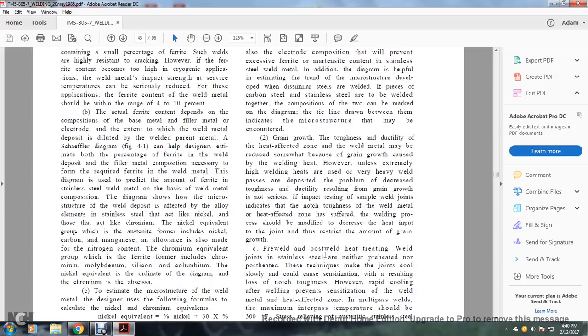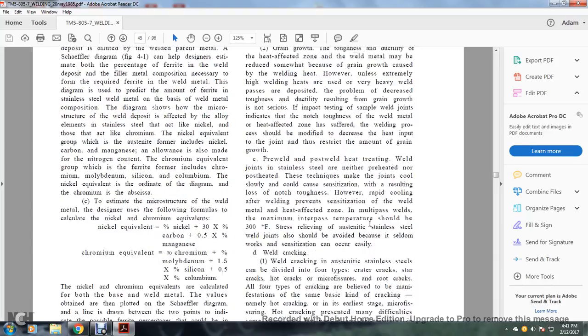Grain growth. The toughness and ductility of the heat-affected zone of the weld may be reduced somewhat because of the grain growth caused by welding heat. However, unless extremely high welding heats are used or very heavy weld passes are deposited, the decrease in toughness and ductility resulting from grain growth is not serious. If an impact test of the welded joint indicates the notch toughness of the weld metal is good but the heat-affected zone has suffered, the welding process should be modified to decrease the heat input to the joint and thus restrict the amount of grain growth.